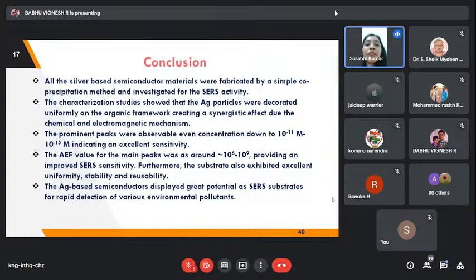And there is a prominent peak observable even at the concentration 10 to the power of minus 11 to minus 15. And then there is an increase of enhancement factor, so the conclusion is that the substrate is suitable for rapid detection of various environmental pollutants.